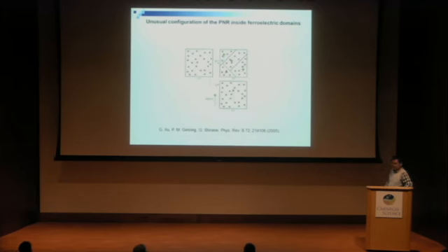To understand this, we use a model we proposed before: at high temperature, the PNRs are almost random. By zero field cooling, the ferroelectric domain is established along different 111 directions, and the 110 type polar nanoregions tend to align perpendicular to the 111 polarization of their surrounding ferroelectric domain. But if we field cool in a 111 field, the ferroelectric domain along the 111 direction will become dominant, and it will enhance all 3 diffuse scatterings coming from the 110 type local polarization associated with this domain.